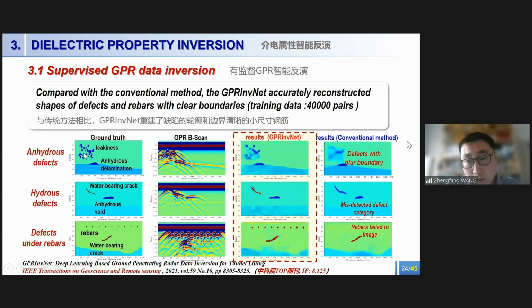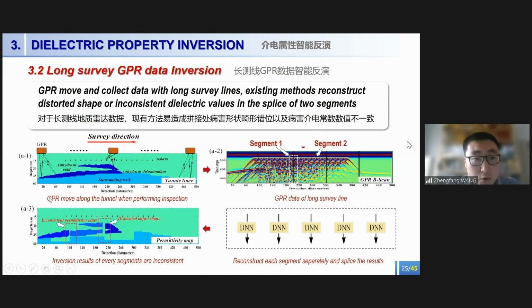Then, as we know, GPR usually moves along the tunnel when performing the inspection, collecting data of a long survey line. The existing method divides these data into several segments and uses a DNN model to process each segment separately and then splices the results. This may lead to distorted shapes and inconsistent dielectric values in the splice area of the two segments like this.